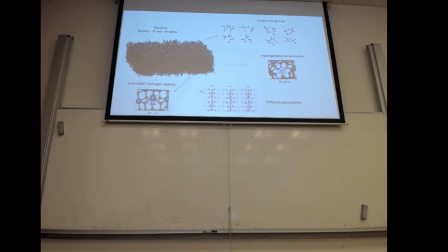Then hydrogen can go into the vacancies that were formed before, when we were discussing the formation of this oxide growth. Basically there are two things. Either a hydrogen can occupy this vacancy, and we see that this is not really favorable. Otherwise, hydrogen can go interstitial, and again there are 3 different ways. It can be charged in different ways, so we have different geometries. So this is the sort of picture of what we have to expect in our alumina when there is hydrogen.